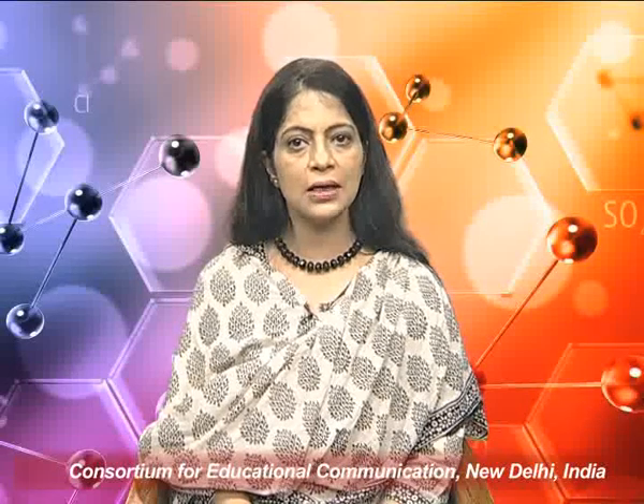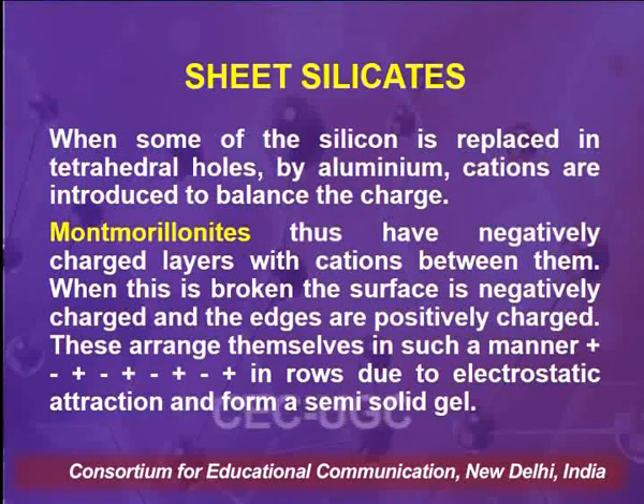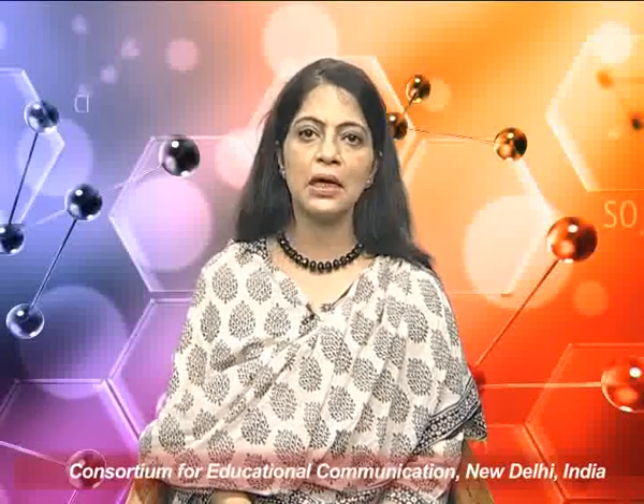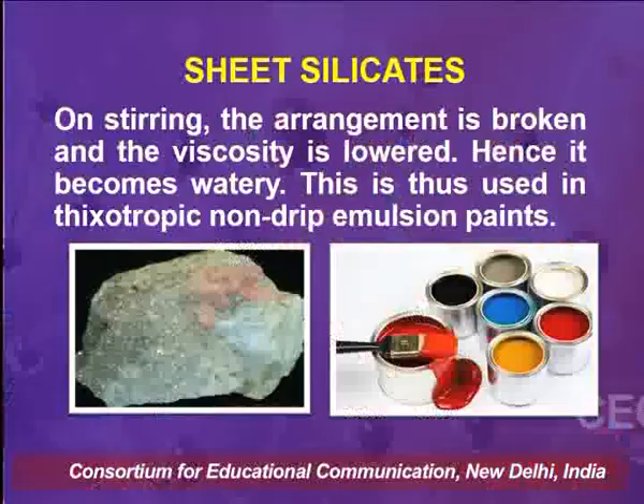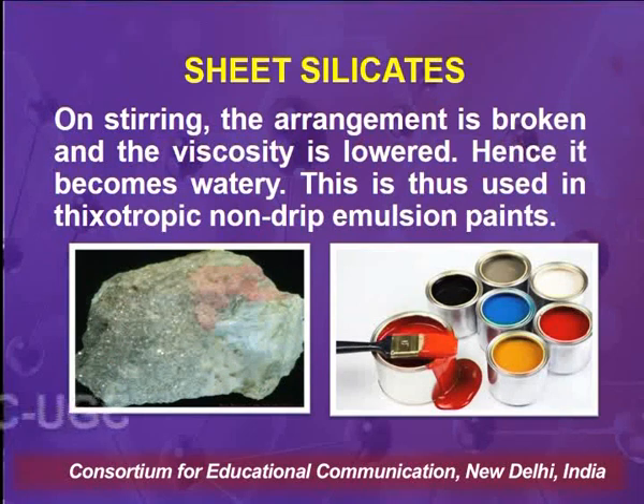These arrange themselves in such a manner, that is plus minus in rows due to electrostatic attraction, and form a semi-solid gel. On stirring, this regular arrangement of plus and minus, or cations and anions, is broken and the viscosity of the Montmorillonites is lowered. Hence, it becomes watery. Thus, it is used in thixotropic non-drip emulsion paints.